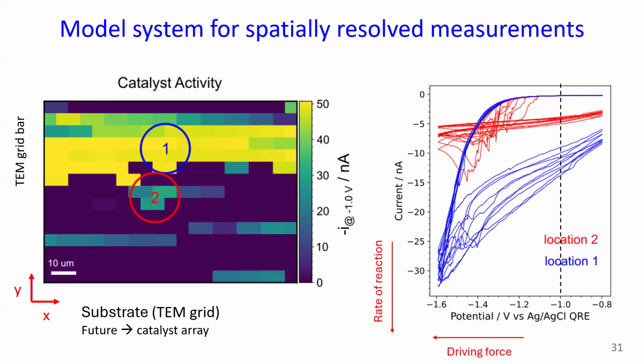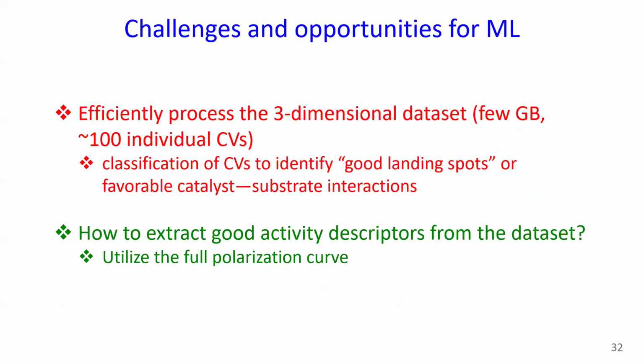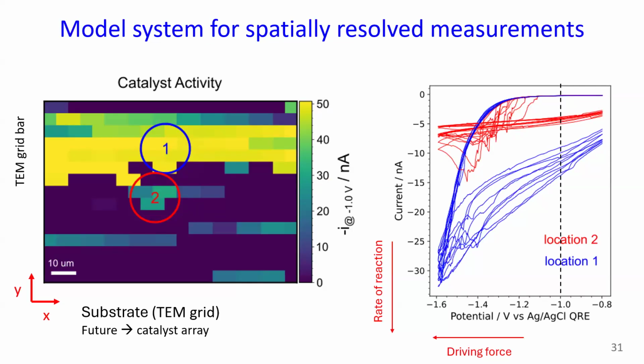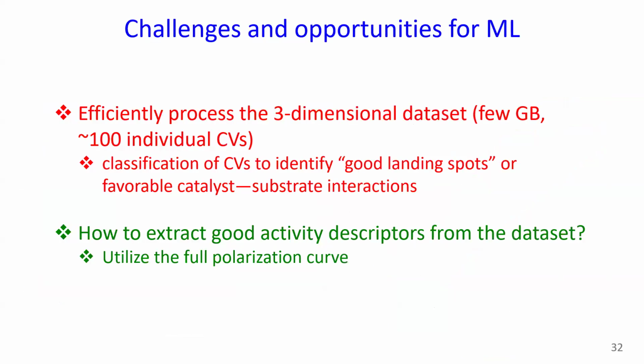We're throwing out 99% of our data, and so opportunities for integrating machine learning into this workflow are, for example, doing a classification on these CVs in order to group them and identify areas on our catalyst array. If we have a catalyst array with 100 different materials, we can do classification to identify groupings, and also extract good activity descriptors from this data set and utilize the full polarization curve. And what's preventing you from doing the full